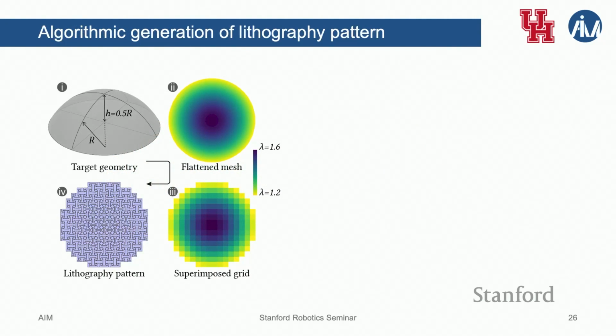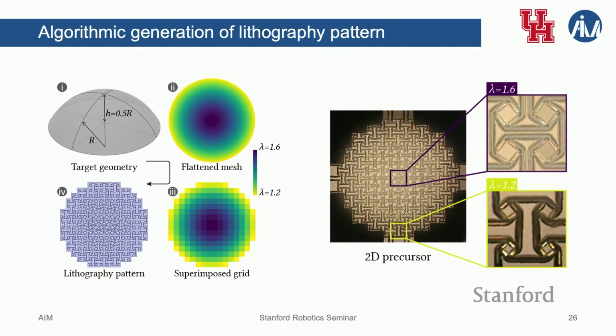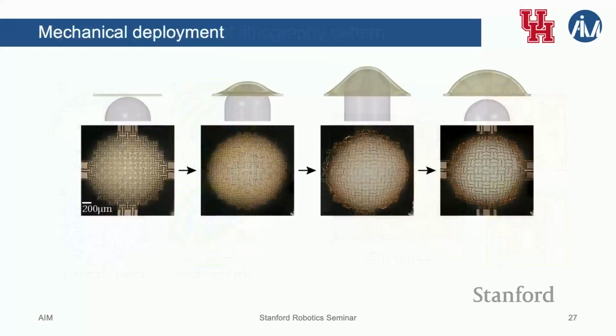And we do this. So this is part of a dome. We do this procedure. We flatten. We lay out a grid on top of this flattened 2D mesh, and from this lambda quantity at every color, we assign a unit cell that matches that lambda, and we tile them together into a heterogeneously patterned sheet. And then we make it. So you can see at the center, the unit cells look very different than at the edges. Pretty understandable, right?